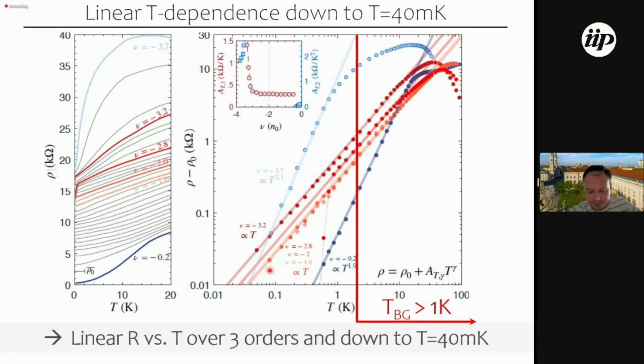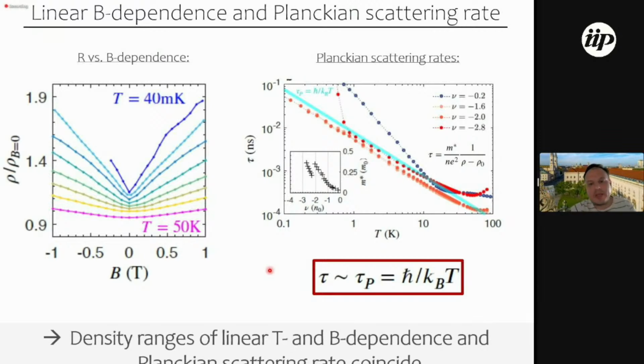So in principle, this is really already a big indication that what we see is close to what is believed to be a strange metal phase. But of course, there are other evidences of what a strange metal phase should look like. So for example, as I mentioned before, one important ingredient is the magnetoresistance that we can measure in these devices. And this shows basically typical measurements. Resistance as a function of magnetic field, where we also find, strikingly, a very linear magnetoresistance in this device. And this magnetoresistance becomes, again, especially predominant in the same temperature ranges that I have just explained, where the strange metal phase lives in the temperature scale.